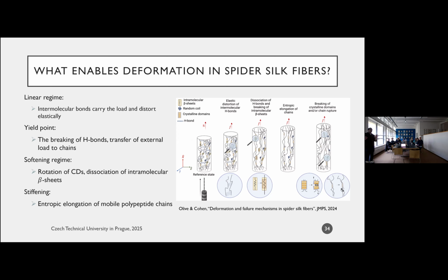In addition, I should also point out, and I'm going to show you this in a second, there is evidence that each of these polypeptide chains has what we call intramolecular beta sheets. So these are basically structures that hide some sort of a hidden length that I can break, right? If I break it, then all of a sudden the chain itself extends its contour length. So that's another mechanism that enables me to get a softening effect. And beyond this point, after the chains have found their equilibrium, if I keep stretching, then I just get the classical response from polymer physics.